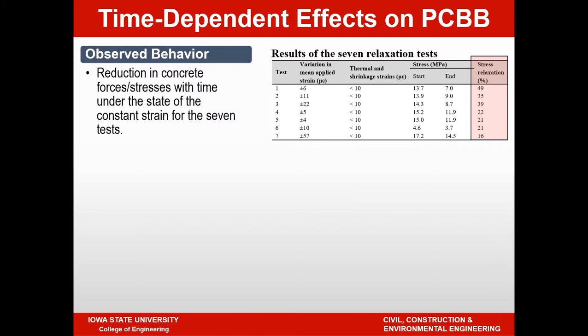or the strains on the reinforcement during the test. Okay, let me just show you some results. It's showing you the observed behavior for all of the seven tests, and you can see that the variation in the mean applied strains was pretty small, so we kept it constant as much as we could. The thermal and shrinkage strains were kept small, less than 10 microstrains. We used a dummy sample to make sure that was the case.